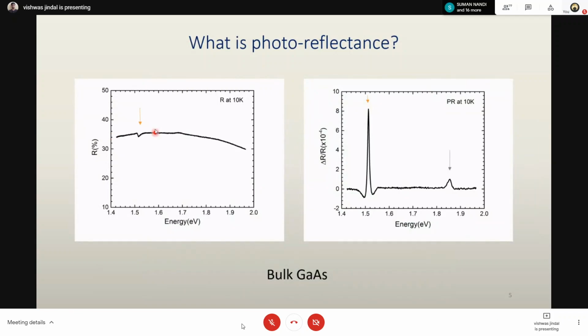In the reflected spectrum, you used a laser pulse also, no? What is the intensity of that laser pulse, in terms of electric field or something? In terms of power, it's somewhere around 400 microwatt, and my spot size is 3-4 microns in diameter, so you can calculate it. Intensity is proportional to one half epsilon 0 E square. You need to know that this is much more intense than the probe light.